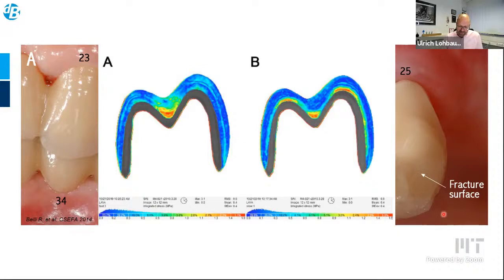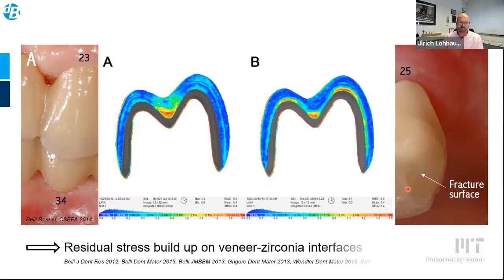This is very well documented in literature, and many clinical studies have shown this fracture incidence, this chipping incidence. And this is an example that from a visual inspection or from a visual finding, we can go deeper and investigate and research into the residual stress state in a material upon the processing parameters, upon cooling such a structure from the sintering temperature. And we did a lot of research, not only us, but a lot of groups that did research on this chipping incidence, and we found that cooling temperature, for example, is one of the major factors controlling the residual stress profile and the chipping incidence.